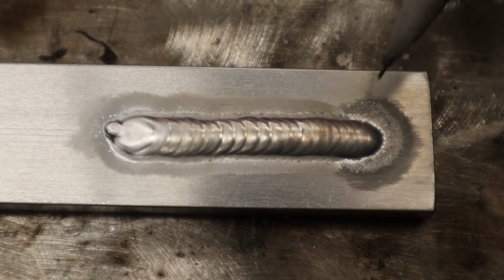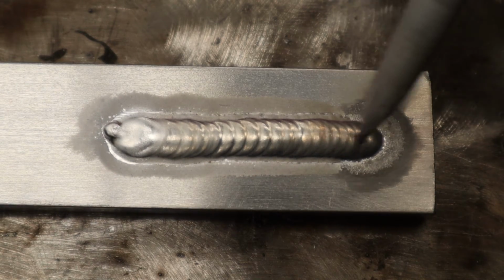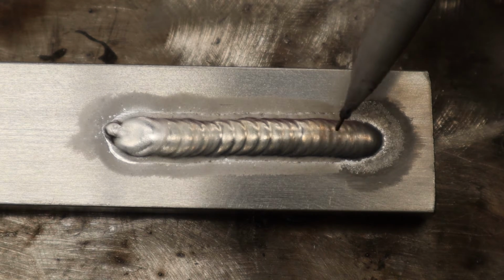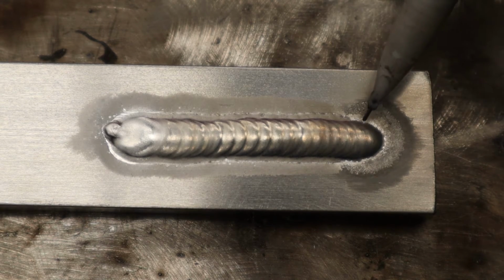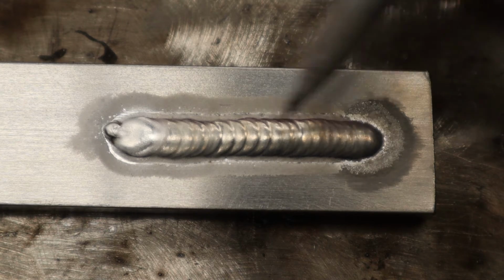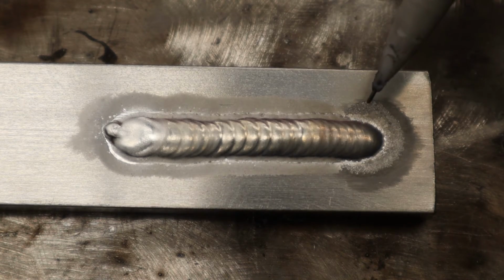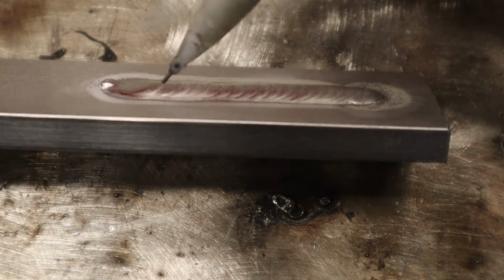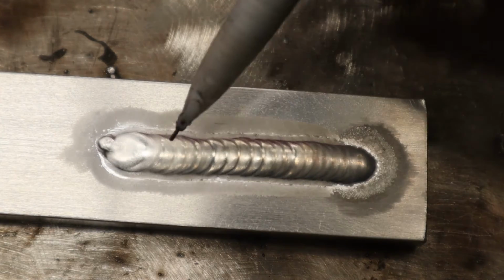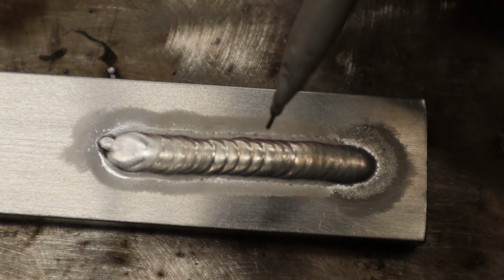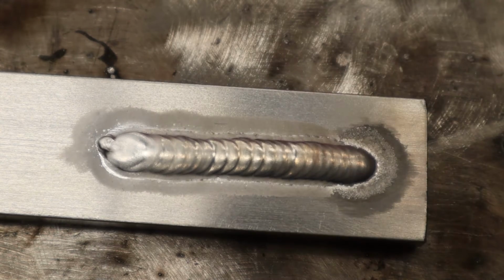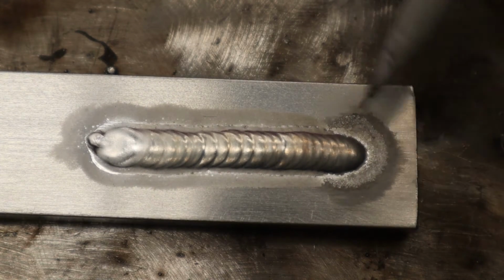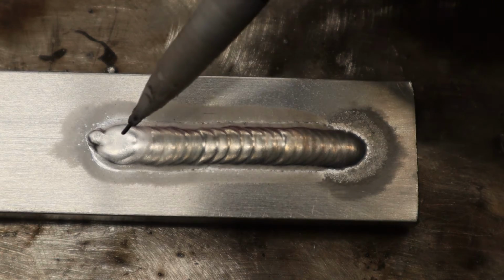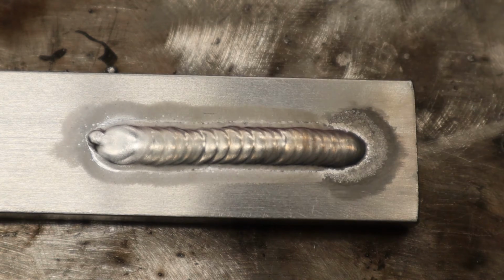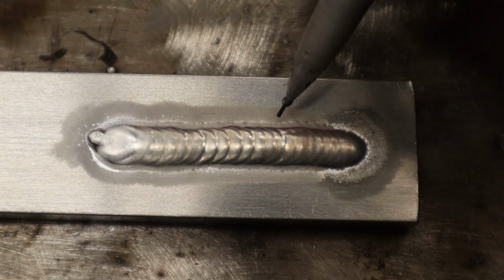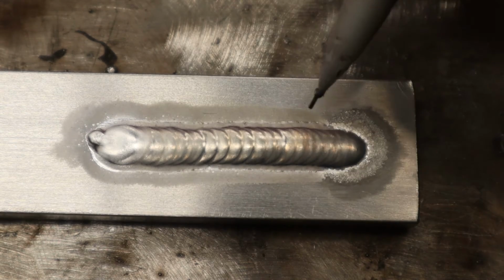All right, let's take a look at this weld. Now, I'm pretty happy right off the bat that it's nice and straight, considering I didn't even scribe a line to follow. The width of the weld bead is pretty even from the beginning to the end and stays consistent. The height stays very consistent from beginning to end. There's no holes, very steady movement. It's almost like a little stack of dimes running along there. There is no hole in the beginning, and there is no hole or crater at the end that could induce some cracking. There is some etching on the sides, and it's somewhat even from both sides.